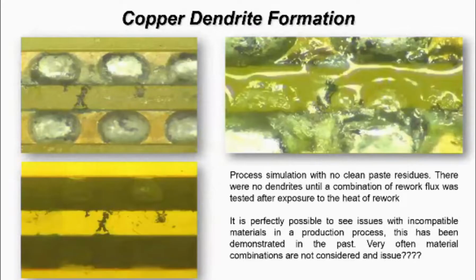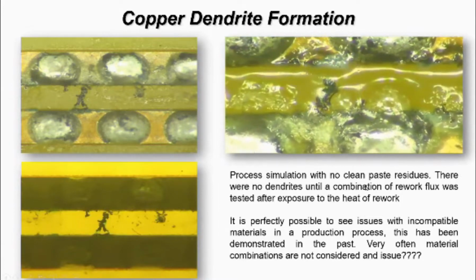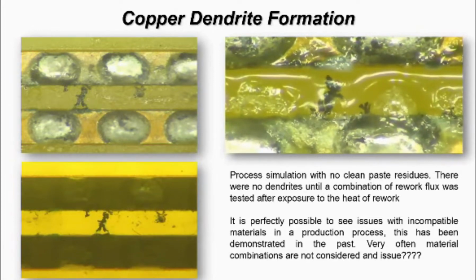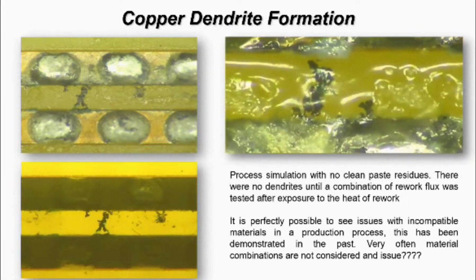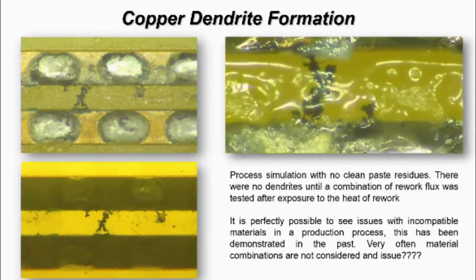And what I wanted to try and prove is that it was a combination material thing. So we took the solder paste, we made some boards, we reflowed them, put them through testing, and were not able to produce failures. As soon as we then continued to rework the packages with a combination of paste and rework material that the supplier was using, we were able to demonstrate failures. As you can see here in the video clip on the right-hand side of the screen, and the 2 optical images on the left-hand side.